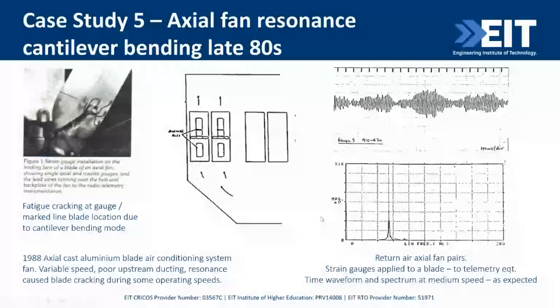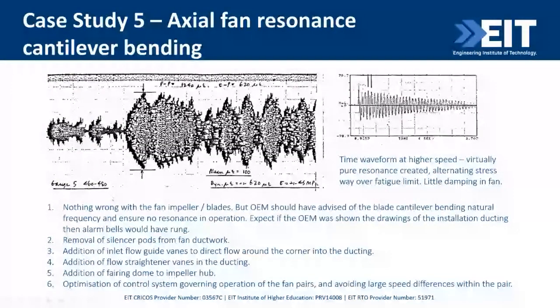So at low speed, narrow band random vibration from those strain gauges. Narrow band meaning one frequency, random meaning obviously random magnitude, but still acceptable. If you increase speed, you go from narrow band random to a 4 or 5 times magnitude increase, and that's pure resonance. The blade is in pure resonance in cantilever bending.